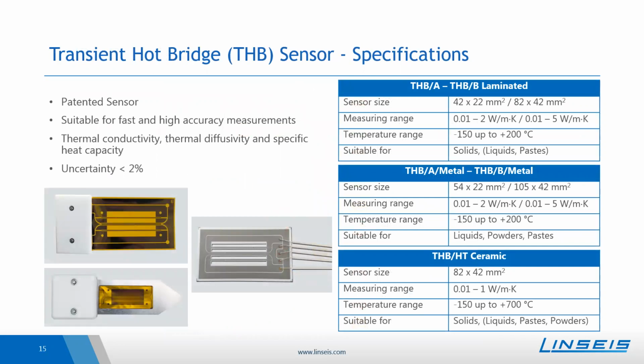Yes, so the transient hot bridge sensor is a patented sensor, and as already mentioned, was developed with the German PTB Institute. It is suitable for fast and high accuracy measurements. One can determine the thermal conductivity, thermal diffusivity, and by knowing the density, one can also calculate the specific heat capacity of a material. It has a very low uncertainty because the hot wires are connected to a Wheatstone bridge, and this enhances the sensitivity. But how the sensor works, I will explain some slides later. Here you have the sensor size in more detail. The smaller sensor can measure up to 2 watt per meter Kelvin and the larger one up to 5 watt per meter Kelvin. And the Kapton foil-based sensors can go up to 200 degrees Celsius.